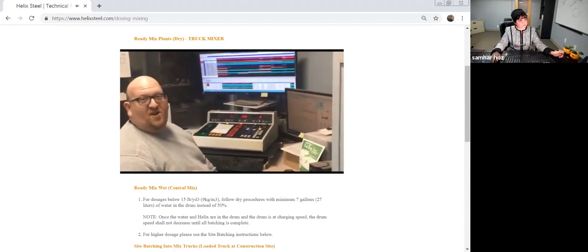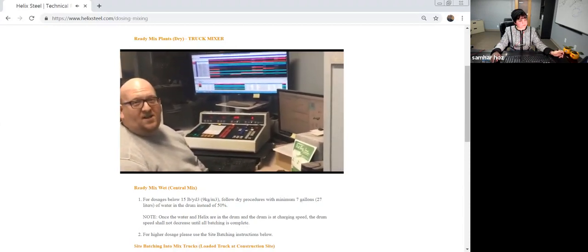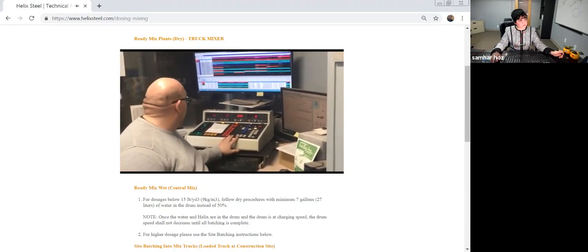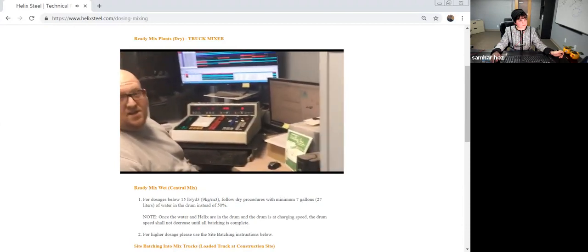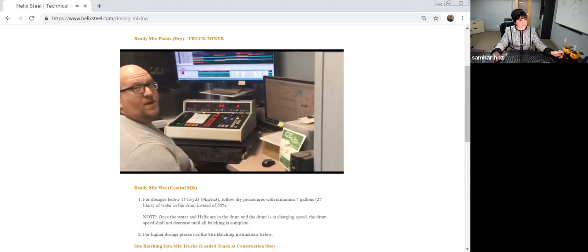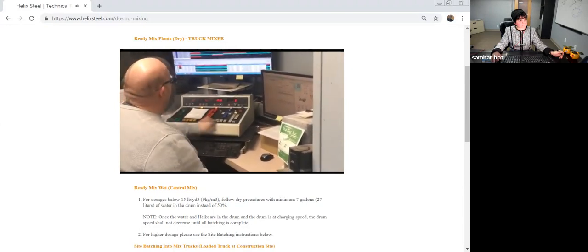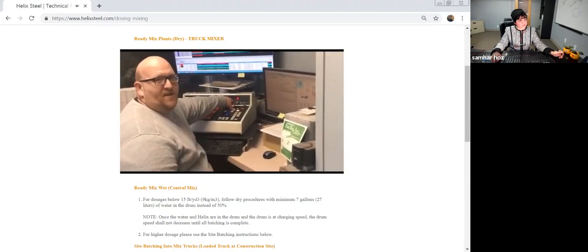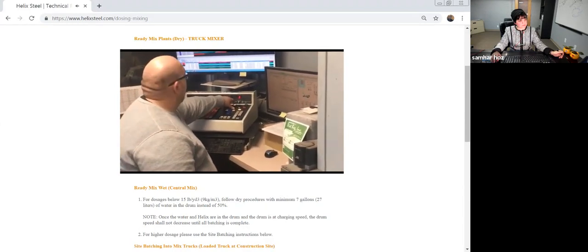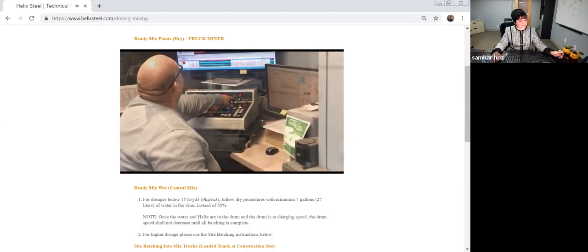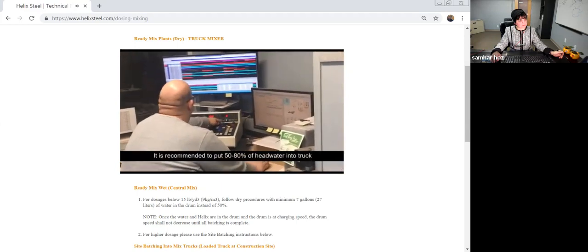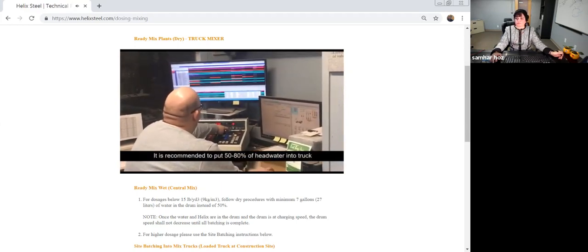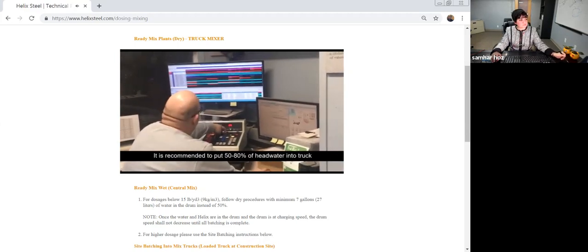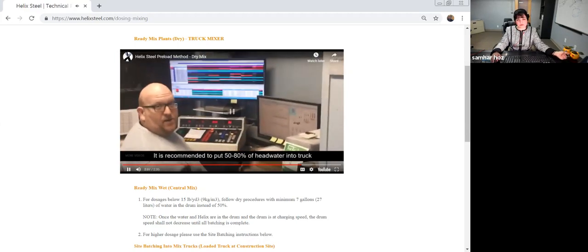Alright, hey, I'm Richard Harden, dispatcher here at Doane Concrete, running an Integra dispatch command batch system. What we're going to do here is throw a little bit of water in this truck. I'm going to let the truck mix up about 45 seconds or so and then proceed with the batch. So I'm about to throw in about 70% or so of the head water and let them mix up. So anything more than 50% would be fine. I'll make sure to distribute Helix throughout the truck.